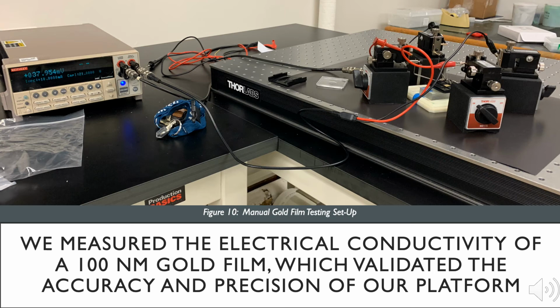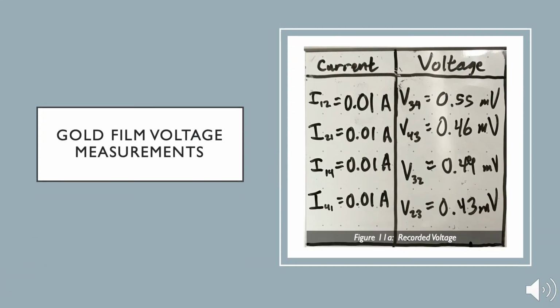Utilizing the van der Pauw equations from Figure 8b, we determined the sheet resistance based on alternating the current and voltage sourced and measured. This resulted in us alternating the corners of the film that were sourcing a current, measuring a voltage, and then averaging each resistance value. To better explain how to use the 4-point probe and van der Pauw method, the next few slides show how we calculated the percent error of sheet resistance of our gold film to a theoretical gold film.